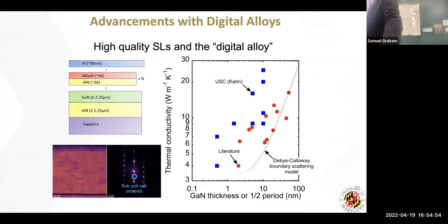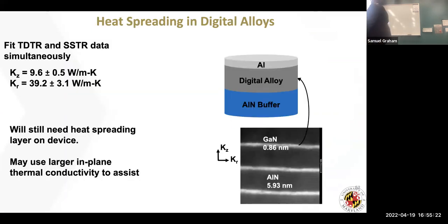So, this is interesting. This plot right here was just put together 3 weeks ago, and this was because of all the measurements we're making. So I don't know if we have the full understanding of where that peak occurs, but what it's showing is that when you look at the gallium nitride thickness overall, as we increase it in that ratio, we're seeing this thermal conductivity go up. And so we don't know where it's going. As you increase the separation, there's going to be something in here where you see how small these are, right? So as you increase this, it's getting better. And then at some point, it's going to look like a superlattice and it's going to turn over and come back down. And so we're not really sure where that point is just yet.